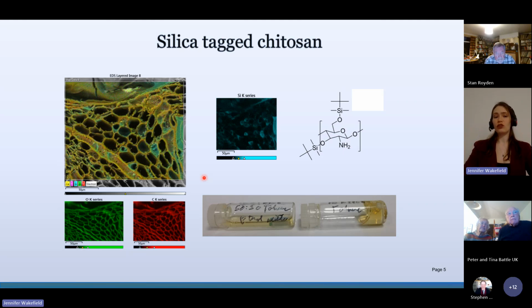But one of the things we also looked at is this addition of the silicon group here. And this is what allowed this to be soluble in organic solvents, which would allow the chitosan to stay in place. And having a look under the scanning electron microscopy with the energy dispersive spectroscopy, it allows you to look at all the elements that are in there. So the thing we could search for specifically is the silicon. So we could see that it was around the edge of the cell wall.